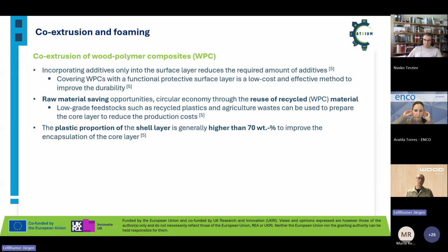And some more words on the co-extrusion of WPC. So it allows us to incorporate additives only into the surface layer, and that helps to reduce the amount of the required additives, and the additives are very expensive most of the time when we're talking about UV stabilizers, to a very small amount. And we can cover the core layer with a functional protective surface layer, and then it also gives the opportunity to use reused and recycled material for the core material. And for example, you can use recycled plastics and also agricultural wastes or waste from the furniture industry, like we do in the ATRIUM project, to form the core layer.